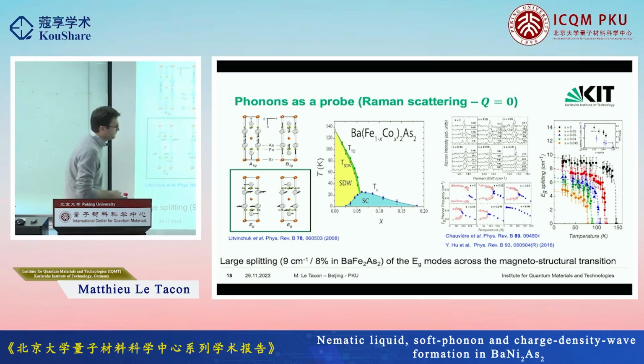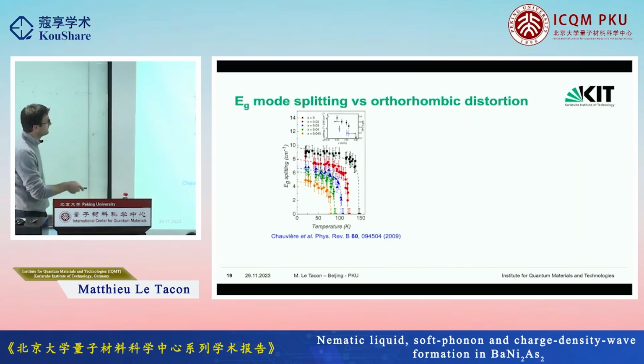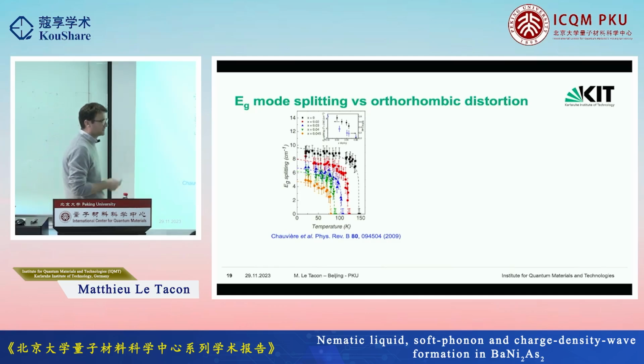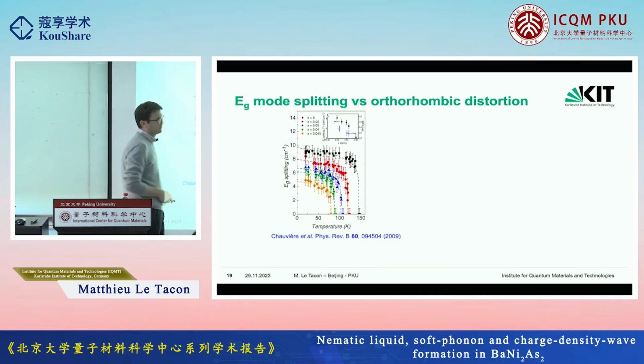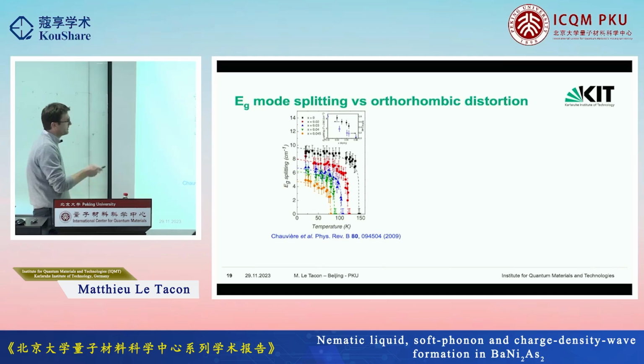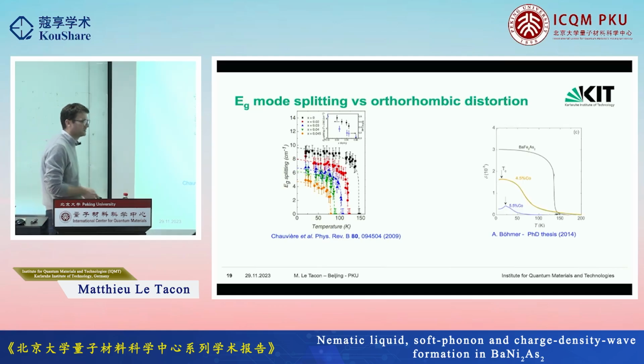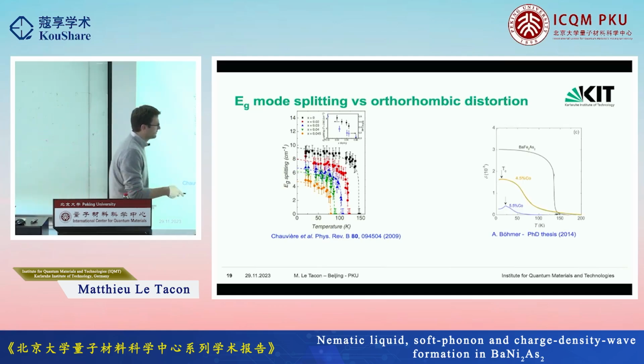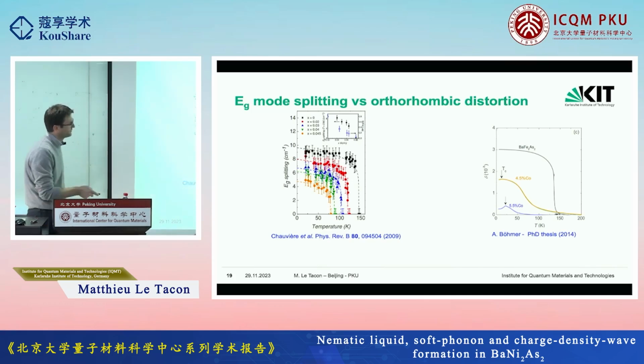The point I'm trying to make here is that if you look at this splitting, you can actually follow the orthorhombic distortion. You can compare that, for instance, with dilatometry measurement. So these are the PhD work of Anna Böhmer, which was in my institute before I arrived, and now is a full professor in Bochum.